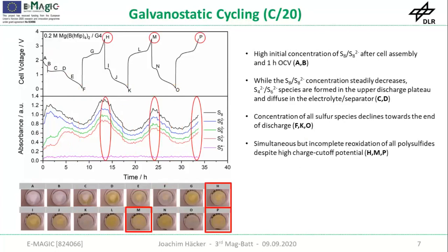Having a look at the subsequent charge, the reoxidation of all sulfur species takes place simultaneously, but it's incomplete. So you find short chain polysulfides, MgS4, MgS6, even at the end of the charge at a quite high charge cutoff potential of 3.5 volts.